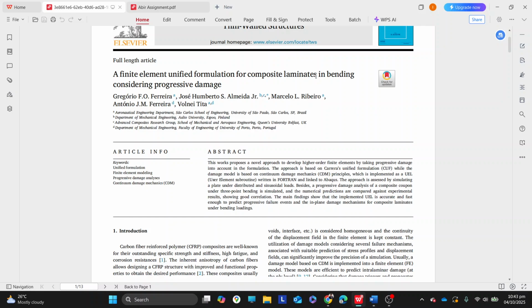From a mechanics perspective, the paper touches both macromechanics and micromechanics. At the macromechanical level, each lamina is modeled as an orthotropic material with three main material directions. Using the constitutive equations of orthotropic elasticity, they captured the stress-strain response under bending. At the micromechanical level, even though they did not perform detailed micromechanical modeling, they relied on micromechanical principles to distinguish between fiber-dominated and matrix-dominated failure modes. This makes the model versatile and accurate without being overly complex.